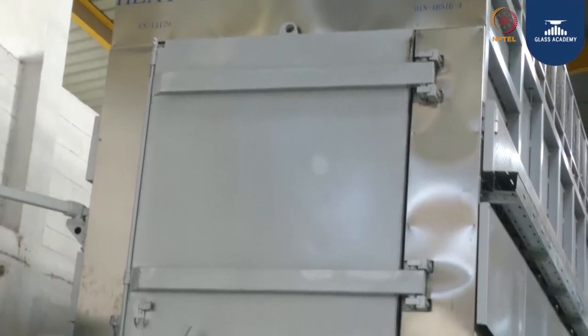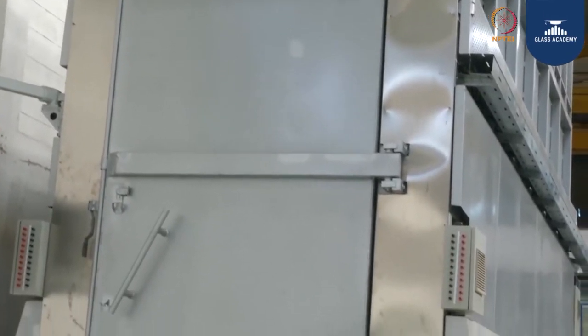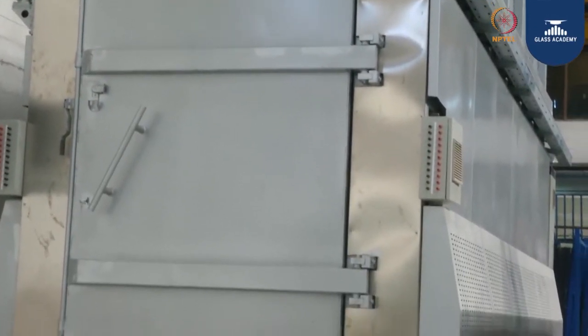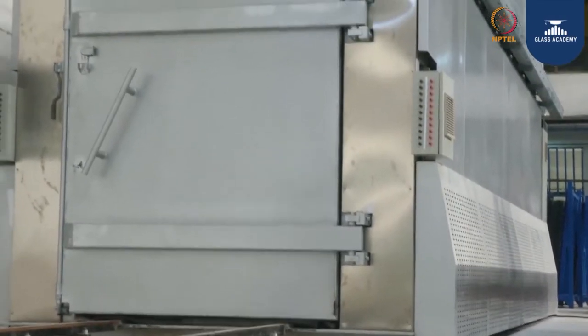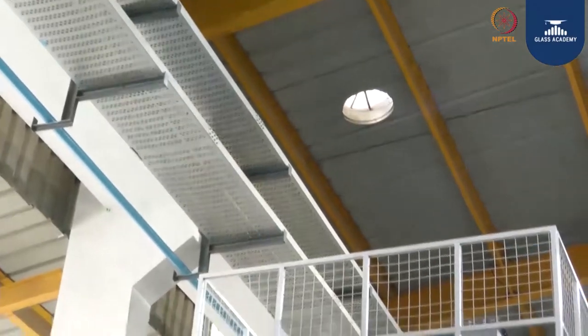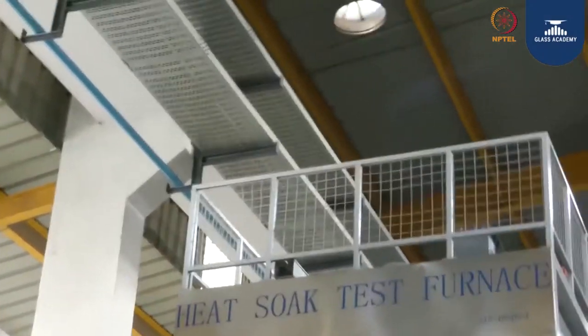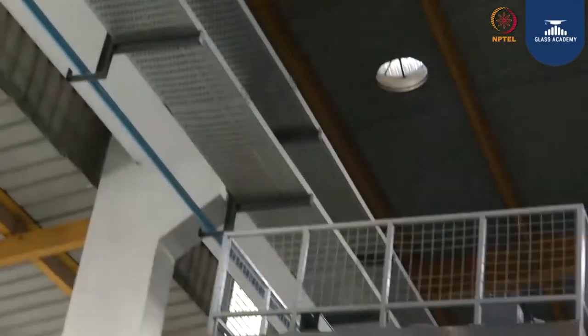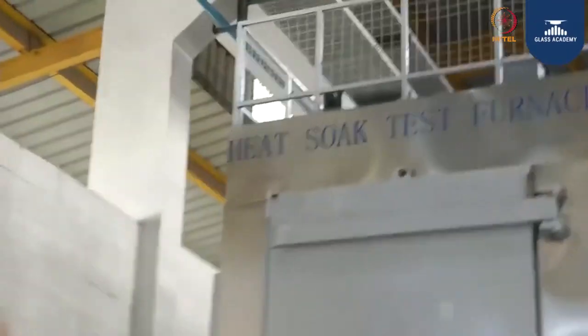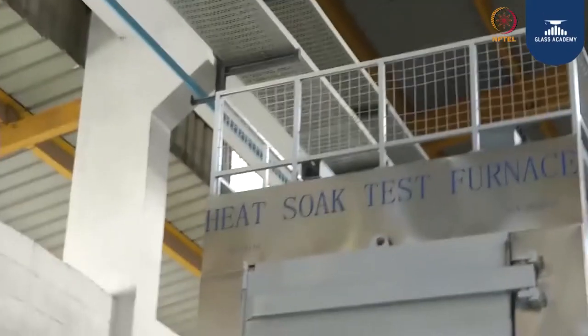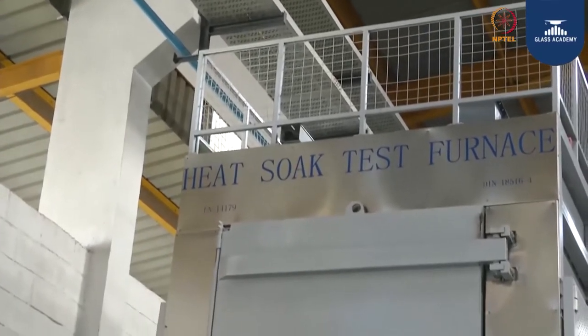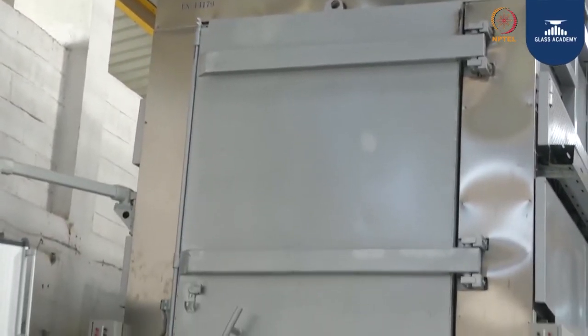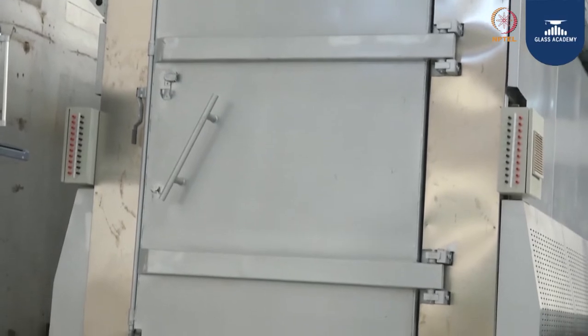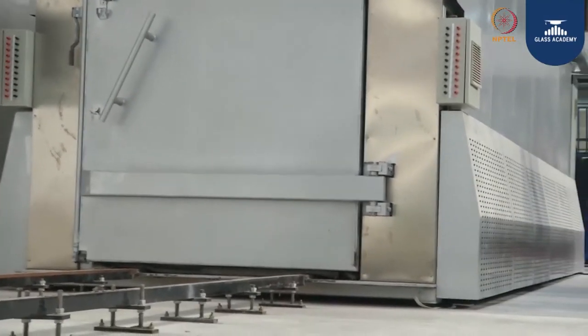Now this is one more machine known as the heat soak chamber. Generally the glass tends to break spontaneously. This is exclusively for toughened glass, because inside the raw material composition there is one impurity known as nickel sulfide. The nickel sulfide content gets activated during the toughening process because it has two phases, alpha and beta, and during toughening it is unable to complete its alpha and beta state. Because of that, the glass tends to break spontaneously.